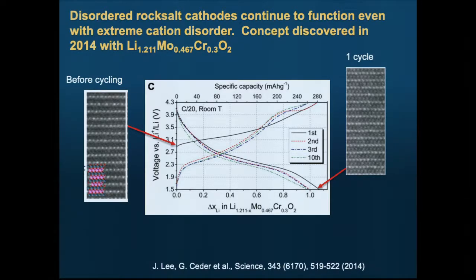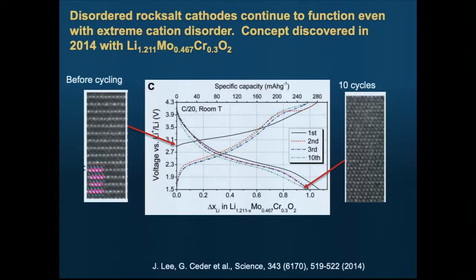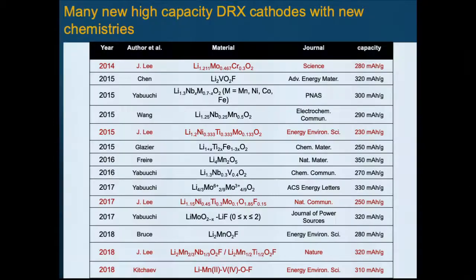So contrast starts to show up in the lithium layer. This is 10 cycles. This is a fully disordered rock salt. But the remarkable thing is after 10 cycles, that's the green line here, we still have full capacity in this material. So this was the first proof of concept that you could actually make a disordered rock salt that had really good lithium transport and lithium percolation.